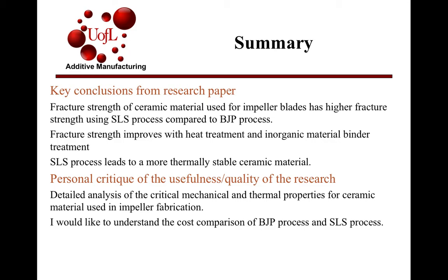The overall conclusions from this paper are that the ceramic material used for the impeller blades has a higher fracture strength with the SLS process compared to the BJP process. Also, the fracture strength improves with heat treatment and with the additional inorganic binder treatments. And lastly, the SLS process leads to a more thermally stable ceramic material.